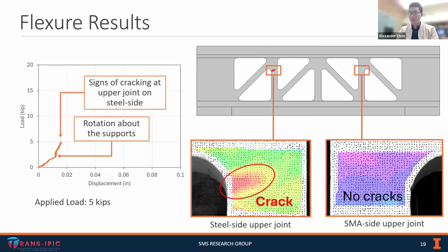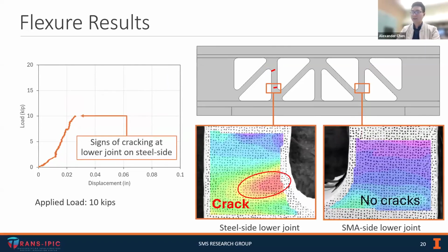And this is indicated by DIC, or digital image correlation, in red. At the same time, on the same sort of mirror image, with the SMA side, we don't detect any cracks. We then kept loading it, and when we reached an applied load of 10 kips, we saw signs of cracking, this time at the lower joints on the steel side. And similarly, like before, there were no signs of cracks on the lower joints of the SMA side.